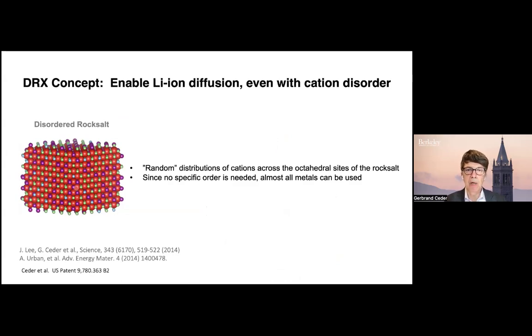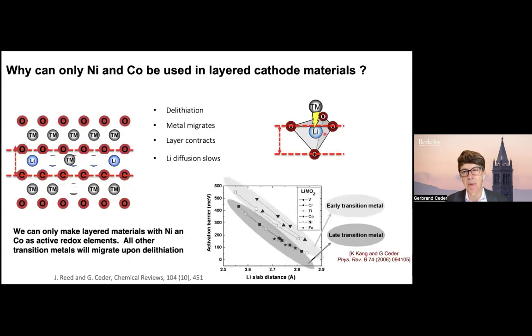So about 10 years ago, we tried to rethink this problem and said, well, we had all tried forever to make layered materials. So we were thinking, how about if we don't need the layered crystal structure, we could in principle use any transition metal. And that meant rethinking the diffusion, and that's what ultimately led to the disordered rock salts. So the whole idea was that if you remember, the real problem is this lithium transition metal repulsion in the activated state. If you were not to have a transition metal there, but a vacancy or maybe another lithium, then the electrostatic interaction would be much less, because you would have 1+ against 1+, or 1+ against 0, whereas the transition metal is typically 3 or 4+.